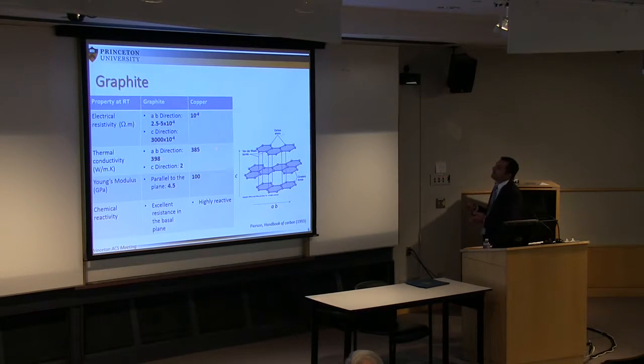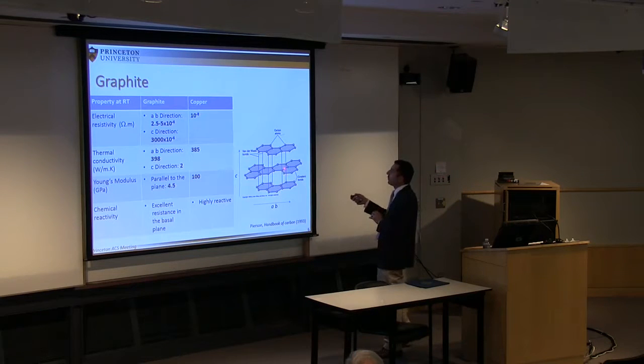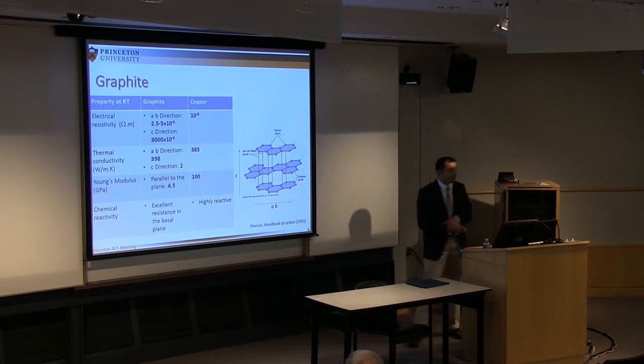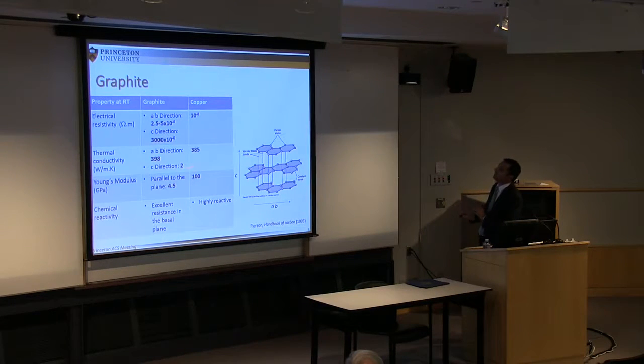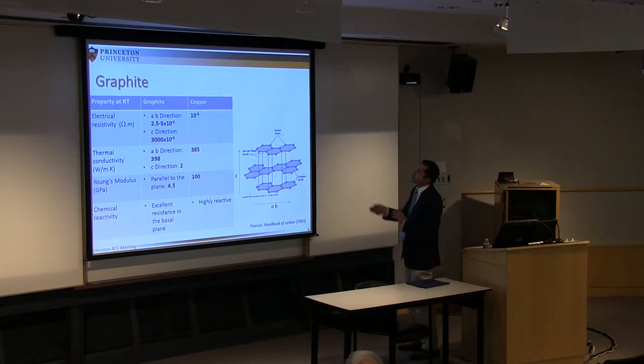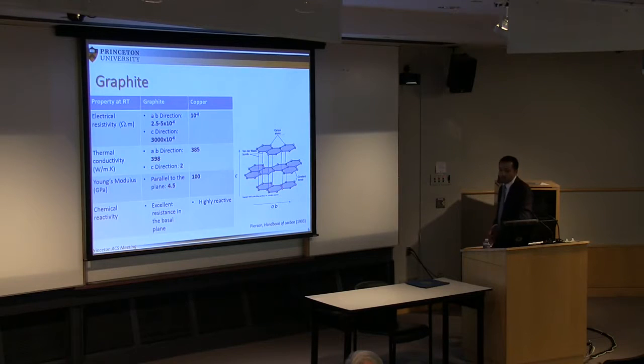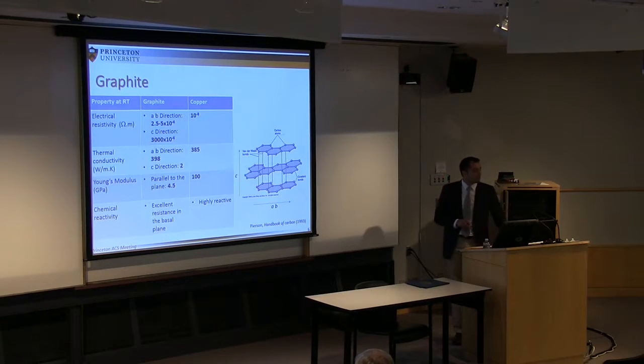If you look at the thermal conductivity, we have more or less the same logic, but we have to talk about the fact that you have less favorable lattice vibrations for the phonons in the Z direction. That's why the thermal conductivity is quite low, 2 orders of magnitude lower. But in the plane you can reach something close to copper. And diamond, for example, has 2,000 watts per meter Kelvin. If you look now at the mechanical properties, again, you have quite an interesting number in the direction parallel to the plane. It's not too far from metal. Combined with an extreme resistance to chemical reactions in the basal plane, this provides a very good field of applications for graphite.